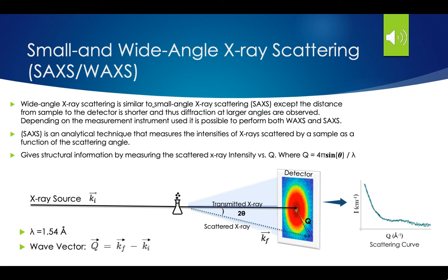I drew a diagram to explain how SAXS works. An X-ray source is emitted into the sample or solvent, and most of the radiation passes through the sample without having an interaction. The scattered X-ray beam creates a wave vector of Q, and the scattered waves are recorded onto the detector, where a scattering pattern is formed and a scattering curve is obtained. You then apply a model and adjust it until a compact shape is found that fits the scattering curve matching the experimental data. This gives structural information by measuring the scattered X-ray intensity versus Q, where Q is 4π sinθ over wavelength.